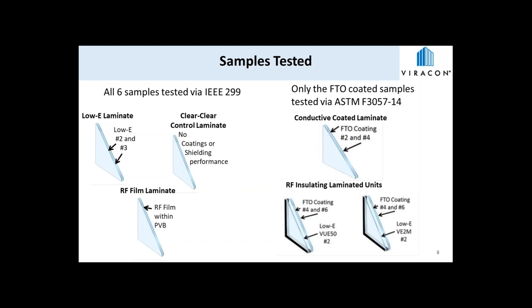FTO. One FTO coating layer was located on the number two surface, and the other was located on the number four interior surface. Having the interior surface conductive aids in creating the metal enclosed Faraday cage that I was talking about earlier within the building. So taking the FTO coated laminate and keeping it on the interior, a laminated unit is then constructed with the addition of a low E coating on the number two surface.